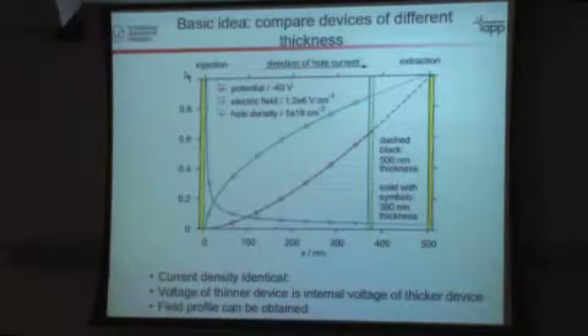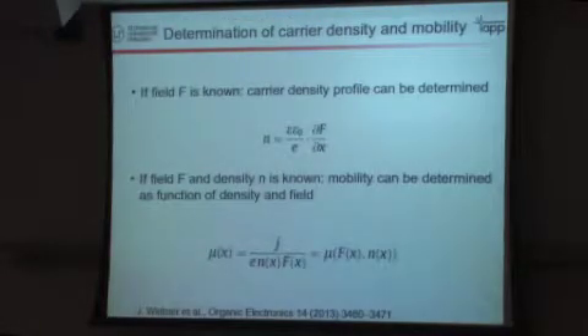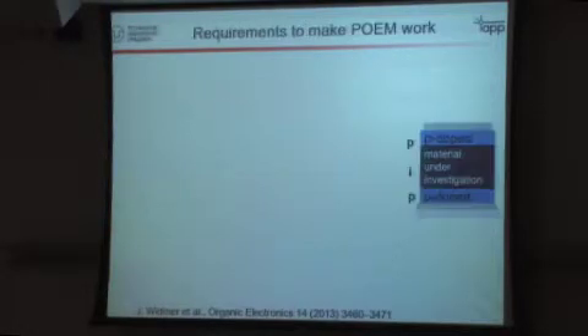And from the potential profile, you can get the electric field profile, and from the electric field profile, using the current, you can get the carrier density profile. So what you simply do is you make a derivative of the potential, then you have the field, and then you make a derivative of the field, and this way you can get the density. And if you know the current and the field and the density, you can actually calculate the mobility at each location of the sample. And since you also know the field and the carrier density at this location, you get what you need, that is mobility as a function of field and carrier density. This theory is extremely simple. You don't need a transport model.